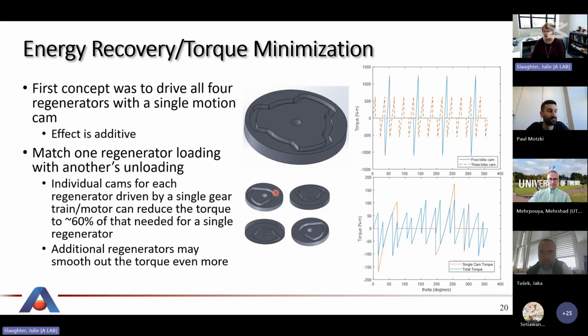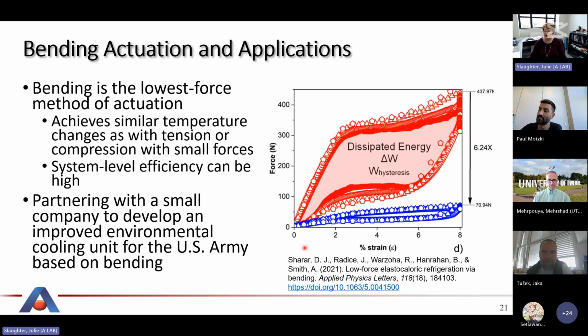So what we're looking at now is driving each of those regenerators independently. If you look at this plot here, the flat areas are where it's either all the way in or all the way out, because you're moving up and down. This is the torque required. This would be a single regenerator, and it goes up to about 175 Newton meters. If we run all 4 at once, and we match the timing so that when one is loading, another one is unloading, we can reduce that to about 100 Newton meters. So we can demonstrate, and this is just models at this point, that we are getting some energy recovery from the system. I think this would be improved if you had more regenerators and improved the timing even more. So that's where we're starting with that. I did want to mention, not going into any details on this, that we are working with a small company that's using bending, which is an even lower force.